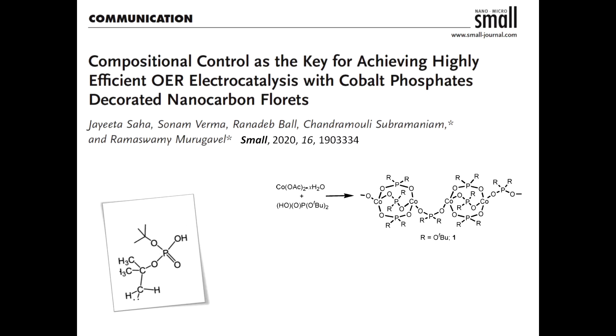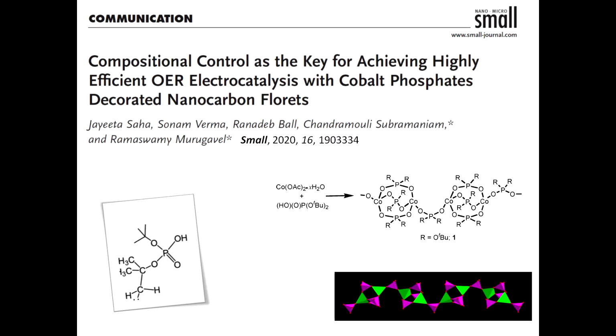So now what you have is this polymer. You can do a single crystal structure. This is what the backbone looks like. A pair of cobalt is triply bridged by the DTBP groups, with these dimeric units bridged by another DTBP. So essentially it's the ML2 polymer.